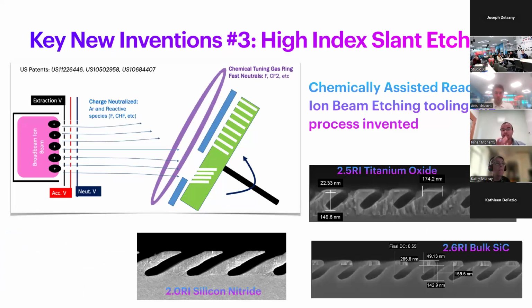Further, this also enabled us to create slanted gratings on various kinds of materials with different refractive indices, such as silicon oxide at 1.46, or silicon nitride at 2.0, or titanium oxide at 2.5 refractive index, and bulk silicon carbide at 2.6 refractive index, which at the time of publication was one of the world's first demonstrators.